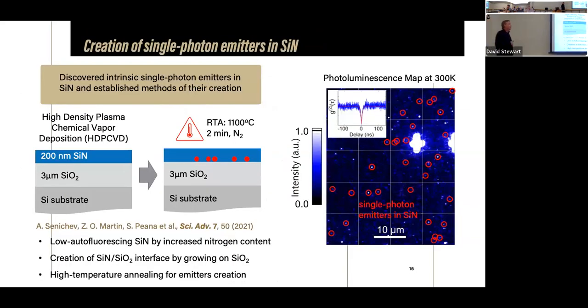So I was supposed to be on this slide. As soon as you use nitrogen enriched high density plasma CVD, you get rid of this background, then you do this rapid annealing, and then you start seeing these very efficient single photon emitters, which we believe are located all here at the interface between silica and silicon nitride.